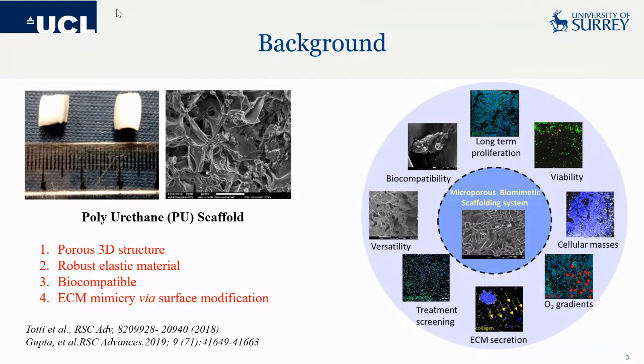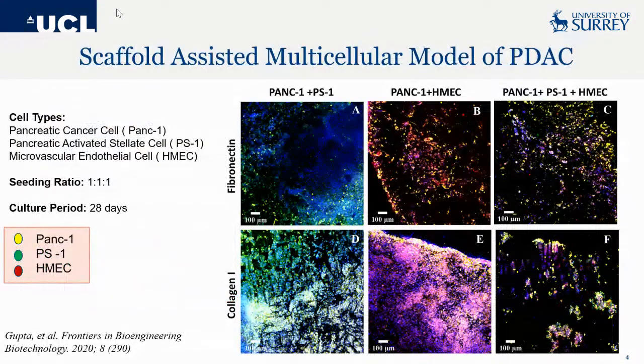In our previous publications, what we have shown is that if you have pancreatic cancer cells on these polyurethane scaffolds, you can have long-term culture of PDAC up to almost 5 weeks. You have proliferating cells which are viable, forming cellular masses. You see expression of HIF-1 alpha in them, secretion of collagen 1 protein by the cancer cells itself. And we have also shown that these multicellular models can be used for treatments using both chemo and radiotherapy.